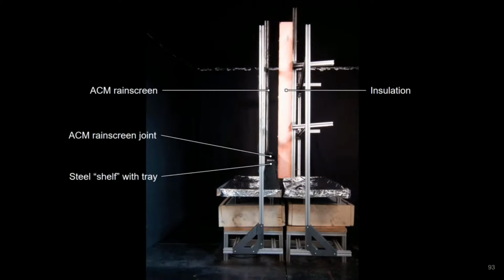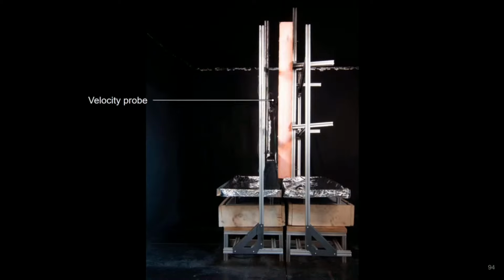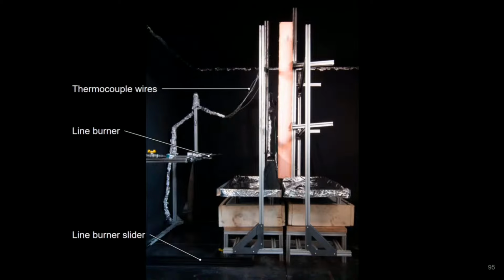The components of the specific experiment being performed, in this case, I'm showing a Reynobond PE ACM rain screen and an opposing face consisting of foil-faced Kingspan Cooltherm K15 insulation, and you can see there's a cavity between the two of about 100 millimeters in these experiments. A velocity probe to measure the airflow velocity at the midpoint of the cavity, and a variable number of thermocouples to measure temperatures at various locations on the ACM and within the insulation.